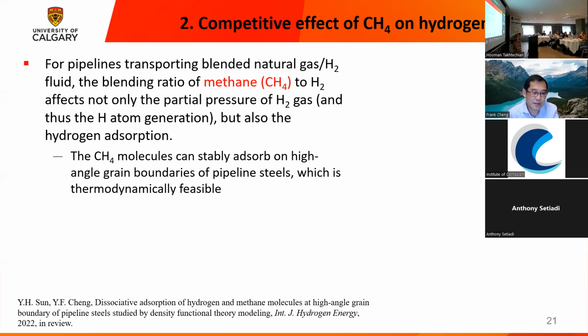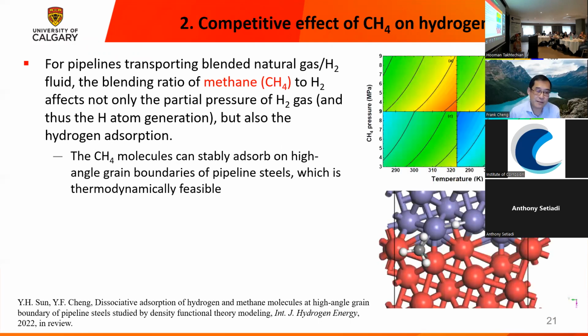determine the thermodynamic possibility of the methane molecule, CH4 molecule, adsorption on the steel surface. So the thermodynamic model also tells us, and you can see from these results, at different temperature and CH4 pressure, the Gibbs energy change, the delta G, is also negative. So that means thermodynamically, the CH4 molecule can also be adsorbed on the steel surface.